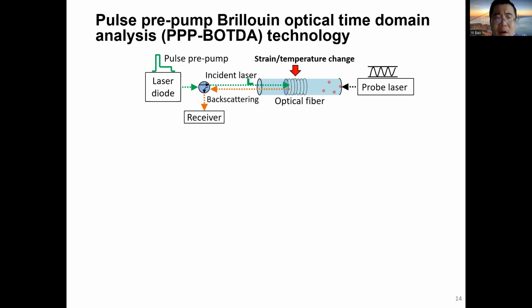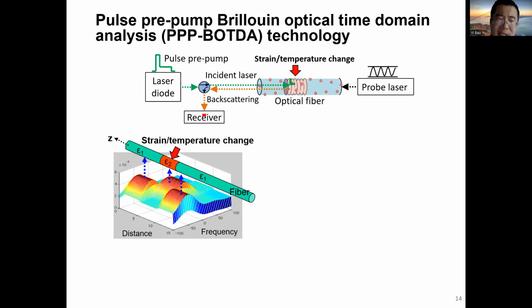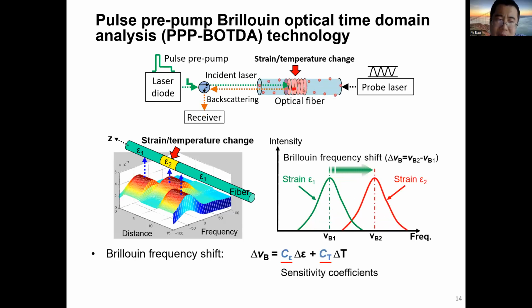So, for example, we have been using so-called PPP-BOTDA technology. When you use this technology, you can beam two lasers, light waves, from the two ends of an optical fiber. For example, at the left end, if we beam an incident laser, this laser will propagate along the optical fiber and stimulate Brillouin scattering through the interaction of light and acoustic signals. And this Brillouin scattering signal could be sensed by the probe wave, which will carry the backscattering information. So if there's any strain or temperature change at a certain length of the optical fiber sensor, then the backscattered signal will reflect this strain or temperature change by showing a Brillouin frequency shift.